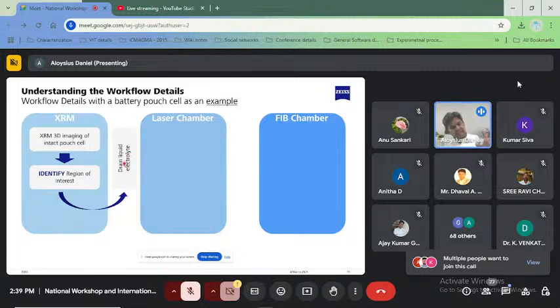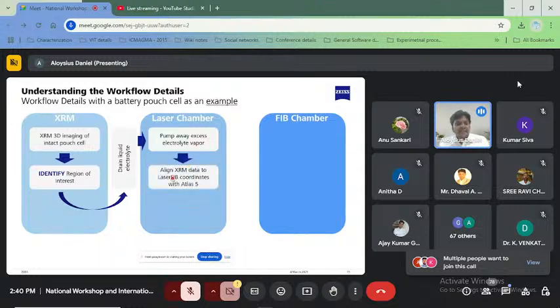Then the liquid electrolyte was drained, and it was taken inside the laser chamber, and all the contamination was removed. The XYZ coordinates of the identified region also get transferred from the X-ray microscope to the laser chamber. It goes to the exact location where it has been identified. Then it starts removing the material using laser ablation. So that's how we access.